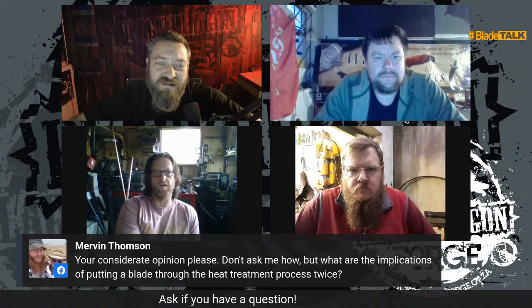I agree with Stu. Every time I see someone do the normalizing and heat treat, it doesn't show up, it doesn't harden, and then they stick it back into another heat treat, I always think, no, your grain growth has gone, you don't even know what's going on in there anymore. No, normalize and redo.